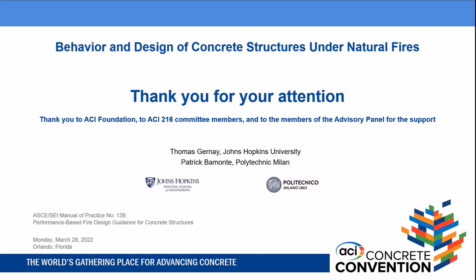But is your question during the heating, if the moisture was monitored during heating? No, I'm saying before heat application. Within a few hours before you started fire testing, were you taking moisture content measurements from the surface of your specimens, checking the relative humidity, and are those quantified somewhere that we could get a hold of them? Yes. I can't tell you by heart the value, but yes, that's in the report, and that was done. These tests were done at Polytechnic Milan.